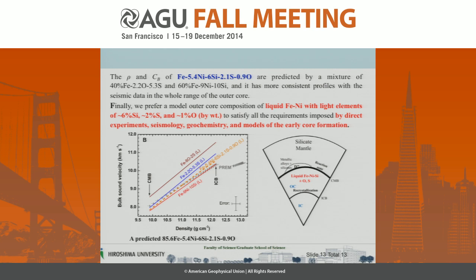So finally, we prefer a model composition of liquid iron-nickel with 5% nickel, 6% silicon, 2% sulfur, and about 1% oxygen to satisfy all the current requirements imposed by experiments, seismology, geochemistry, and model compositions of the Earth's core. That's all. Thank you for your attention.